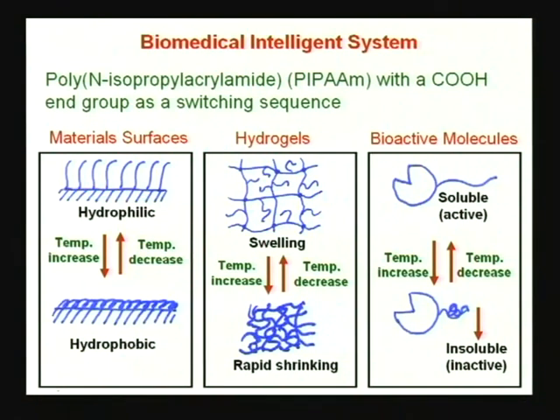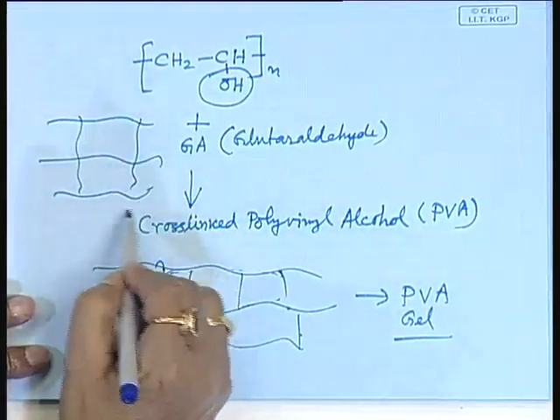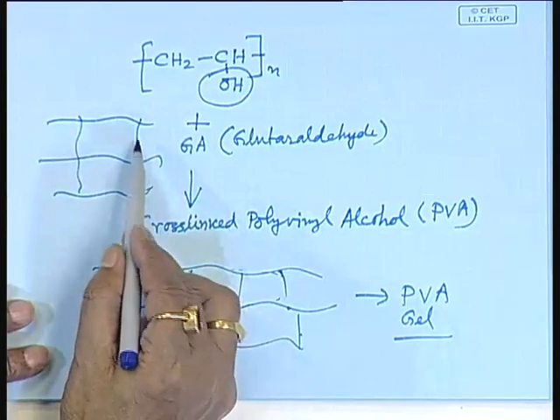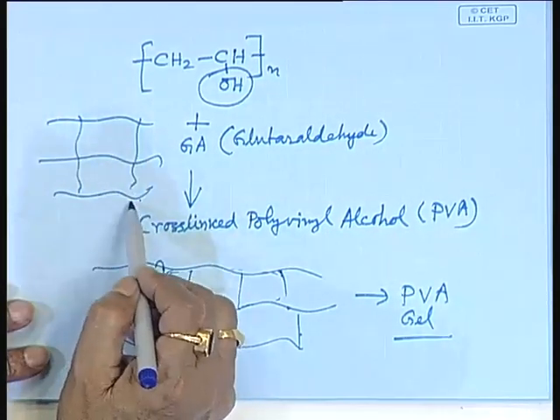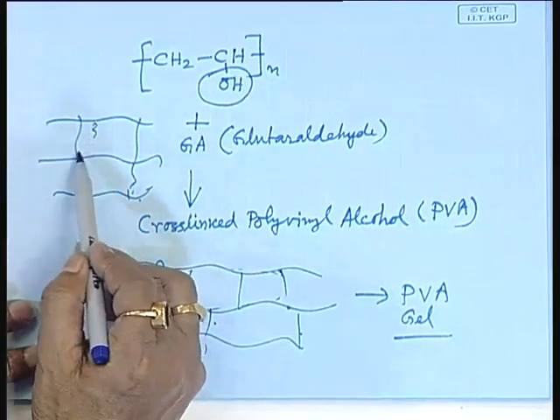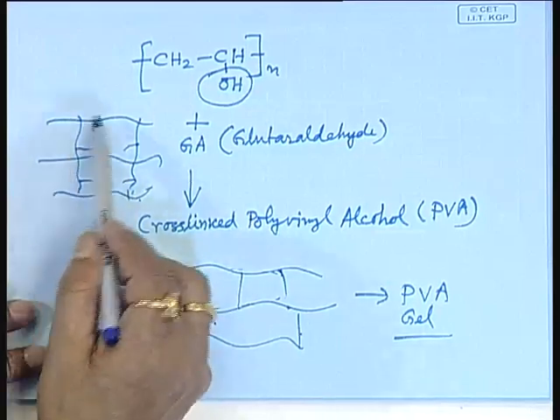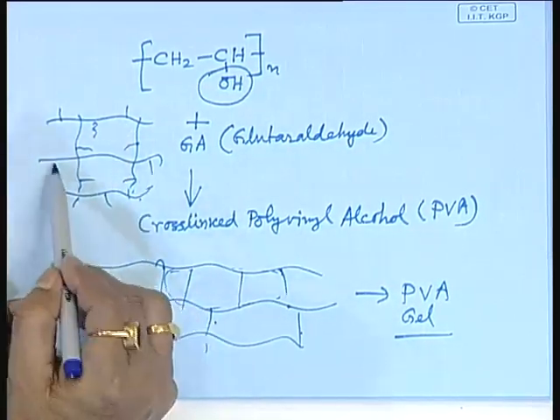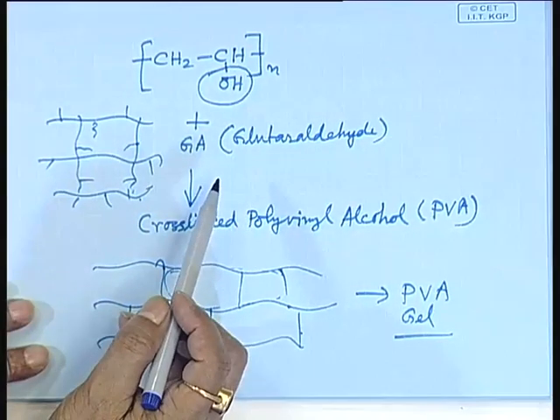Now, the same thing has been extended to hydrogels. You see, this is a hydrogel. These lines are polymers, where the linear molecules are interlinked through these bonds. Now, onto their surfaces, smaller lengths of these thermoresponsive polymers are linked, or modified. So, this gel has become thermoresponsive. That means, with change in temperature, it can either swell or shrink.